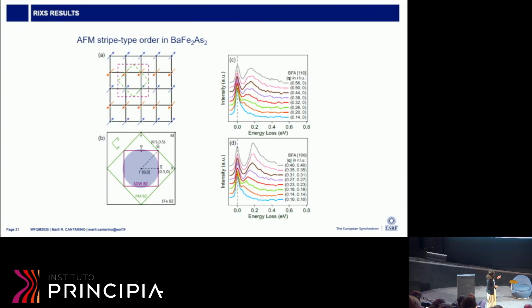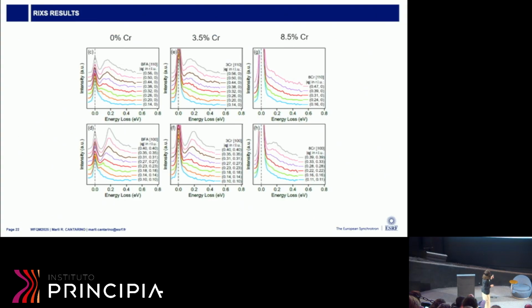When you look at the results of the parent compound, this is the magnon peak after we subtract some other contributions at higher energy loss. You see the dispersion of the peak as a function of momentum, and different peak shapes in different directions of reciprocal space. When you look at the doped sample, the 3.5% chromium sample is very similar to the parent compound, doesn't change that much. But when you go to the 8.5% chromium sample, the magnon is much more damped and lower in energy.